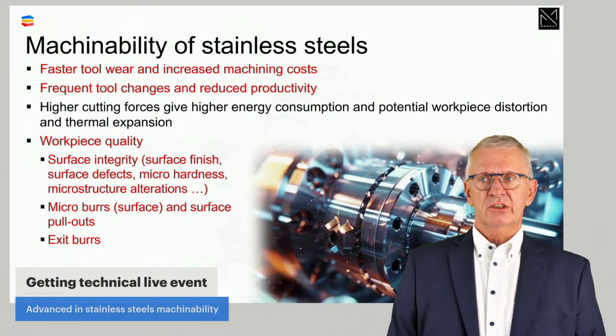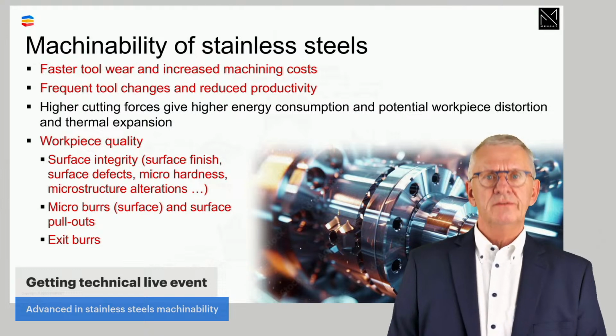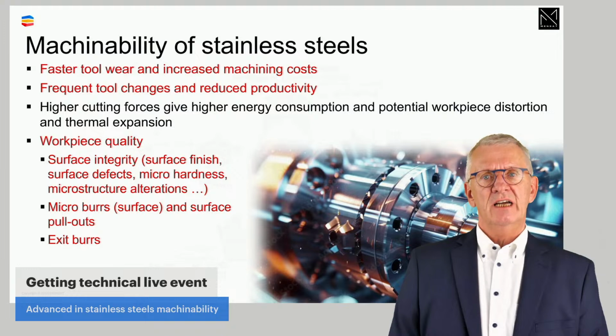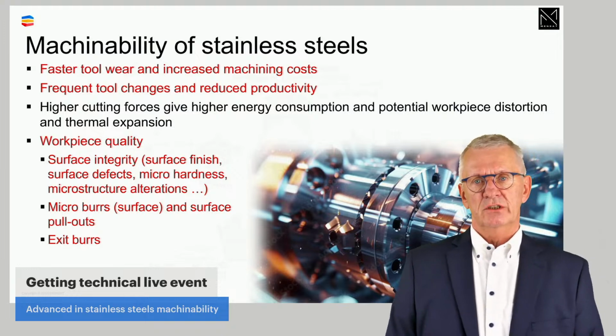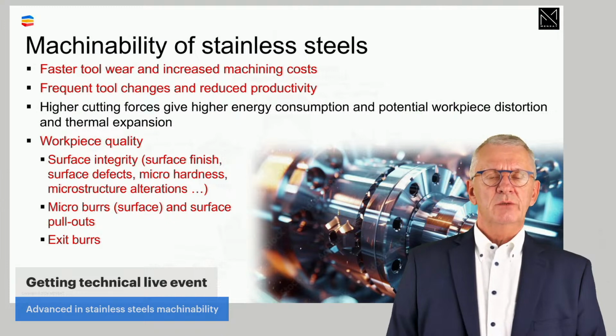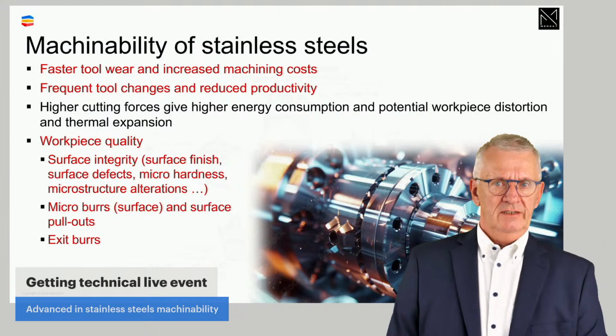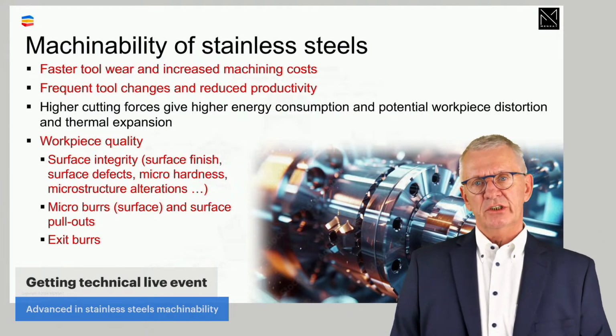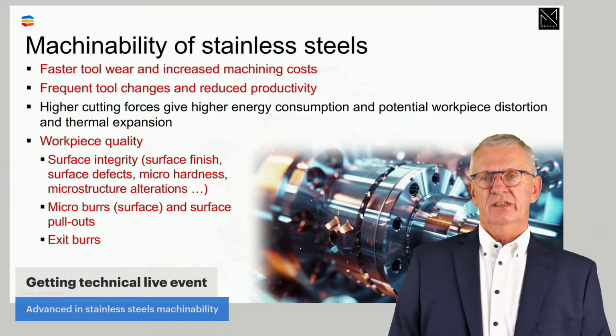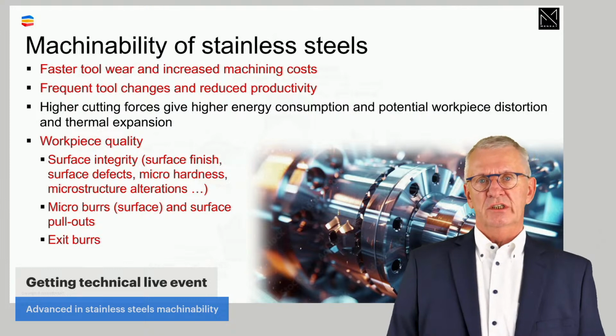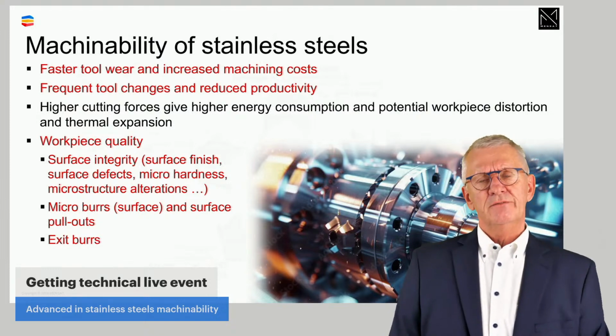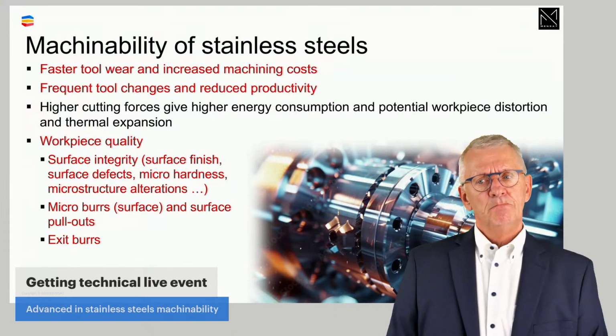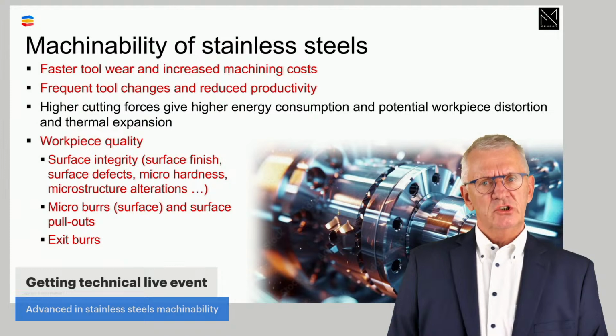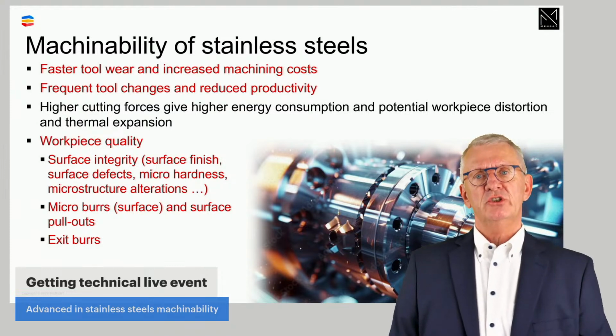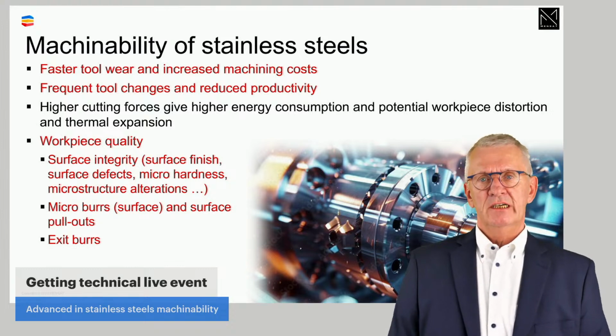Anyway, in machining of stainless steels, tool wear will be faster than what you are used to. That means that in general, machining costs will be higher than the ones we normally have in traditional steel machining. Tool changes will be more frequent due to shorter tool lives in general. And if you have more frequent tool changes, your machines are going to stand still, relatively seen, more than in steel machining, and that's going to lower your productivity. On the other hand, if you look at workpiece quality, you are going to be confronted with some things that will demand post-machining processes, deburring and such, and that will also lower your productivity.